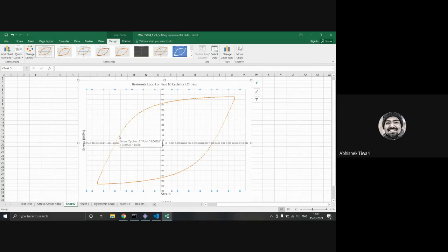Then you take all these data points and shift them on a coordinate axis, keeping the point where the loading starts, 425, and shift the abscissa value there to 0. Once you shift it to 0, you can go to an offset. You don't actually need to shift it. You just draw a line at an offset of 0.002, parallel to the linear part, and wherever that intersects, that should be the yield strength.